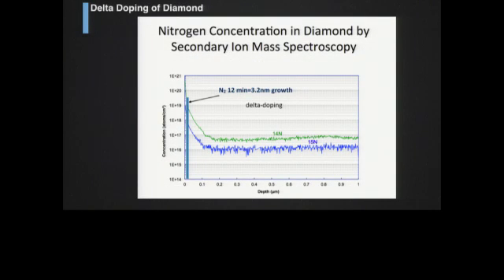We've also put a spike near the surface, so we slow down the growth rate, and a 12-minute growth produces about a 3.2 nanometer thick layer of nitrogen near the surface, and then we see how that nitrogen has been spread out as a result of that. And if you calculate the diffusion length, you'll see that for this material, the diffusion length is pretty wide. And so when you try to put a very, very thin layer of nitrogen in, it does spread out a little bit.